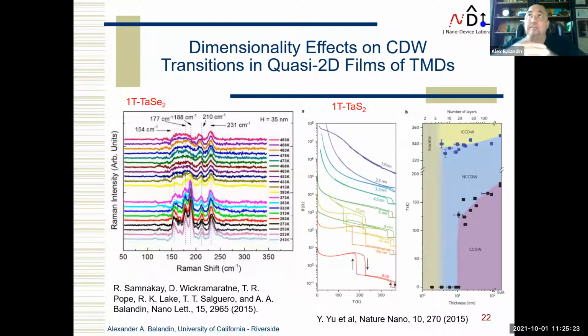Okay, so now dimensionality, thickness of these materials also plays a role, because in work from other groups, they show that if you change the thickness of this film, the transition temperatures may change. That is because going to the charge density wave phase is an interplay of how much energy you spend to distort the lattice and how much energy is released to go to the new ground state. So of course that balance would depend on thickness. Initially my group started to work with 1T tantalum selenide, and we looked with Raman spectroscopy at how we can move the material up and down at different thicknesses. The point of transition we could observe from the Raman spectrum, because when you go to the incommensurate phase, translation symmetry disappears and Raman peaks become flat and wide.